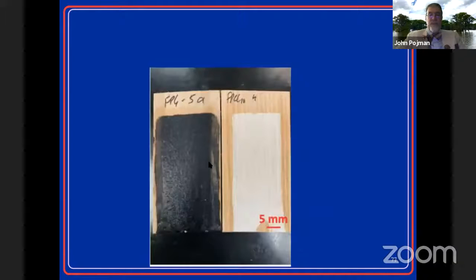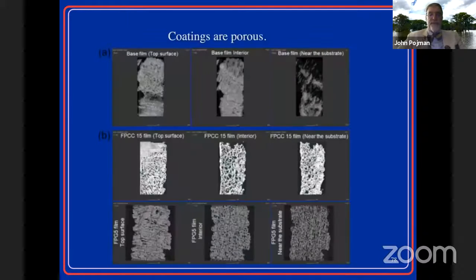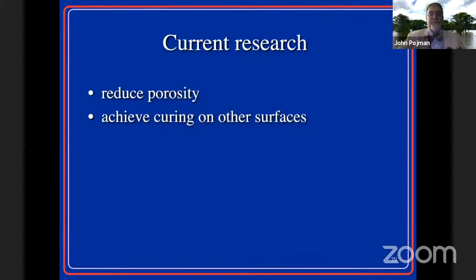And this is an example of what the cured layer looks like. This is on pine wood. One problem is the coatings are rather porous. Doing micro CT, microtomography on it, we can see that it's about 30% porous. And that's caused by byproducts of the polymerization reaction, the initiator decomposition. So one area we'd like to work on is trying to reduce that if you want to have a more solid material.